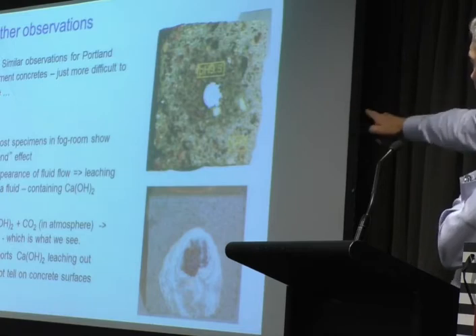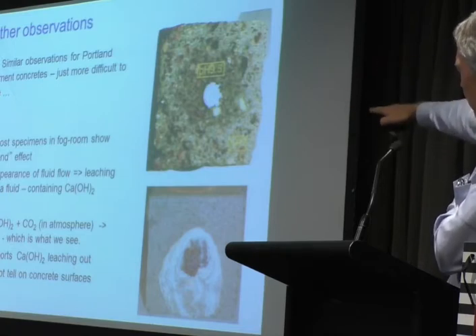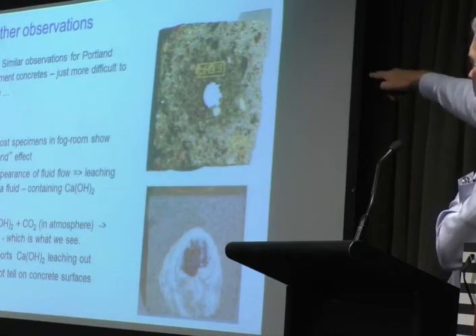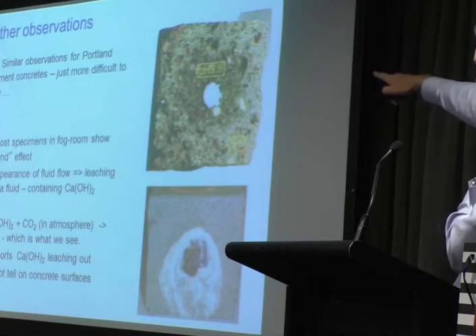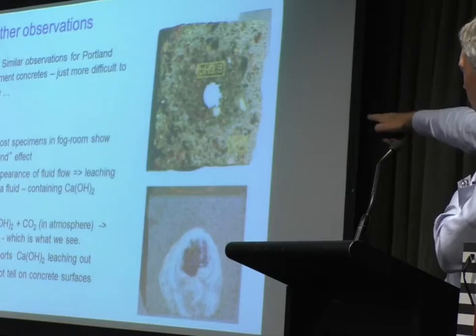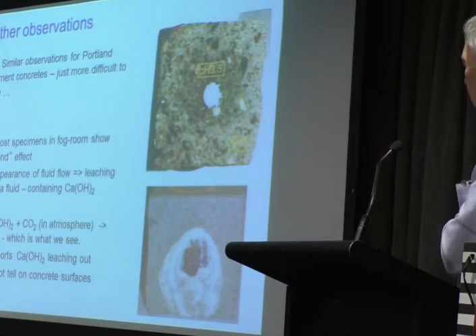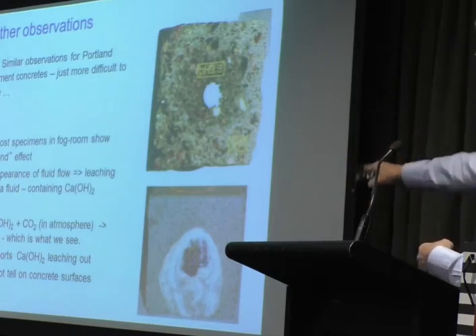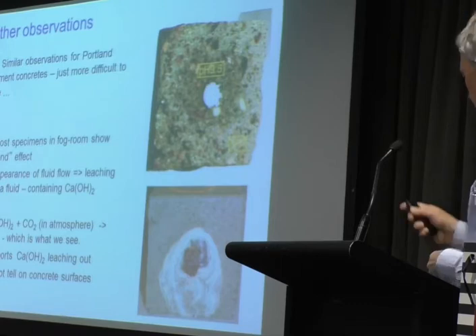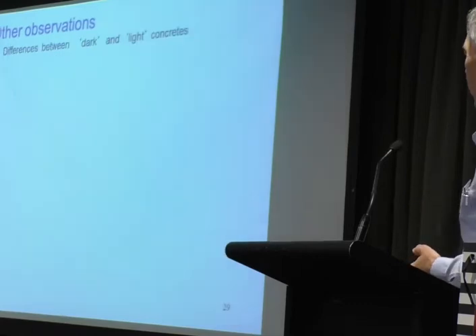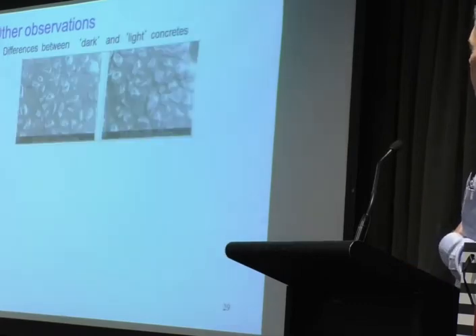Much more difficult to see, but if you look at the pHs, you can see that even in an advanced state, the pH is still above 9 in the middle and no corrosion of the bar. These are cross-sections cut with a saw, and the pH on the outside is a lot lower. And if you look at the very outside of the bars, we often saw calcium carbonate formed there, and that's what you would expect. So, difference between the light and dark concretes.